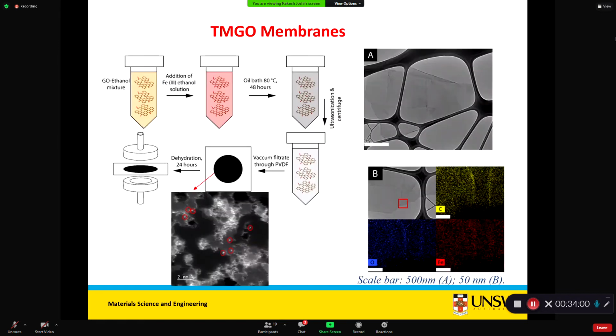Then what we did, we made a new class of membranes. We call them transition metal incorporated graphene oxide. Here again we used Fe. We incorporated Fe into graphene oxide, and these membranes are made in ethanol because we want to have no moisture on the membranes. We made flat membranes of Fe incorporated graphene oxide. We see the monolayer quality of graphene oxide, single atom Fe here, and nice distribution of Fe throughout the membranes. And these TMGO membranes, we then use them for gas separation in flat membrane form. We haven't done the tubular membrane work on this one.